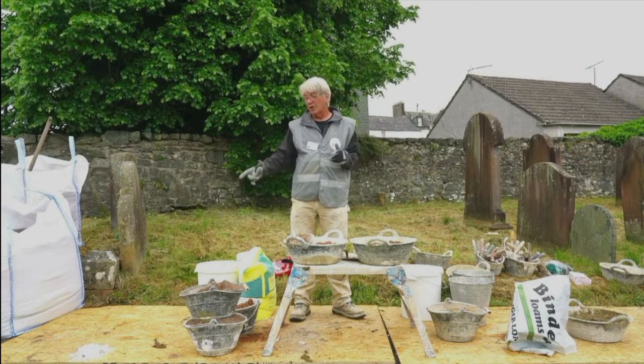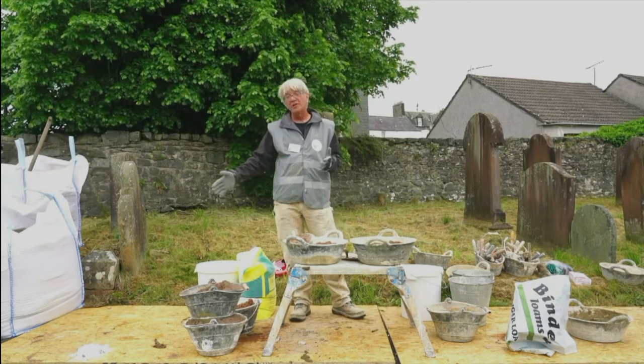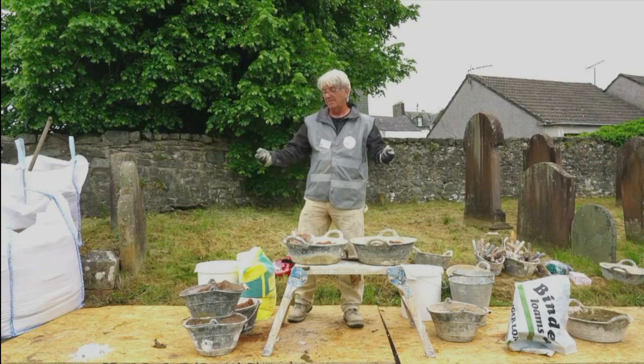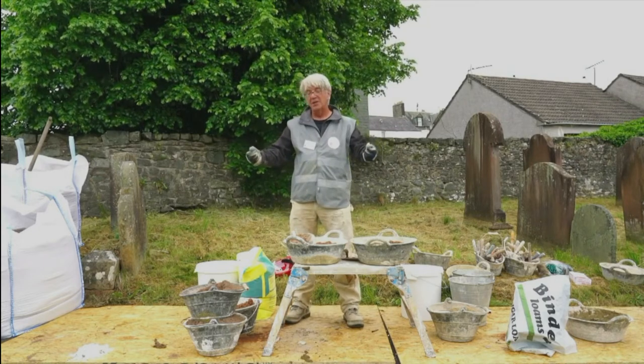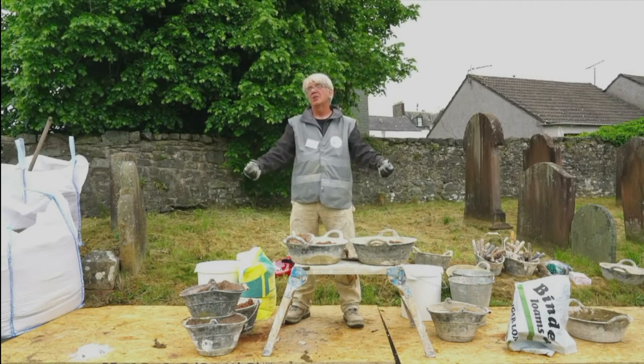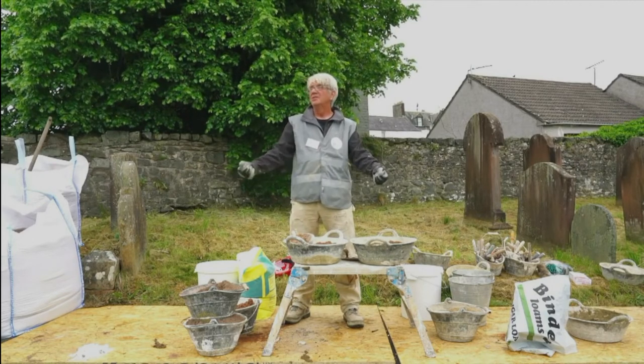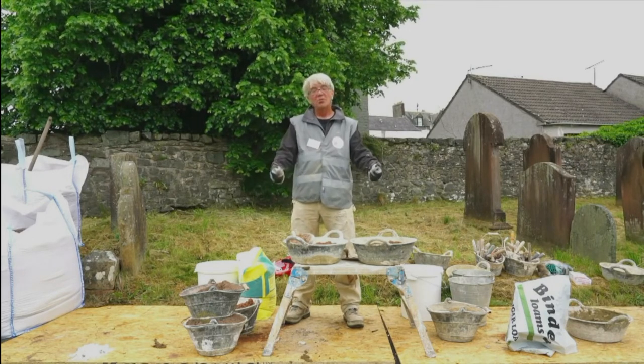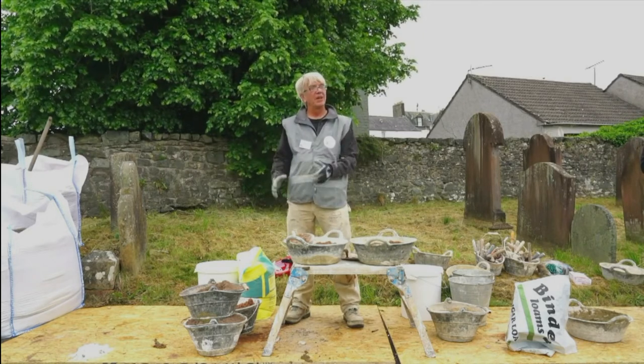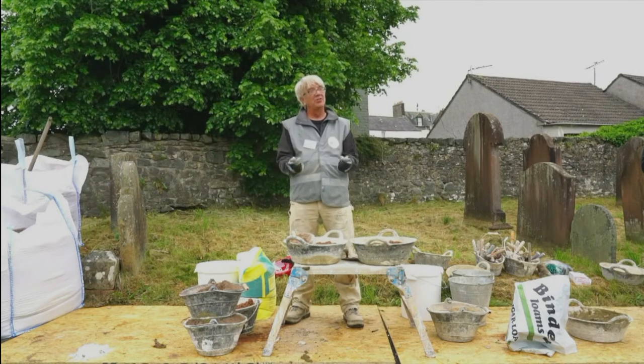So when they were dry slaking, there's two ways of making a hydrate on site. They would get an open weave basket, put the lump lime in it, hold it underwater for a couple of minutes till it had stopped soaking in the water, tip it out, and it was slaked to a dry hydrate. They could then sieve that hydrate.